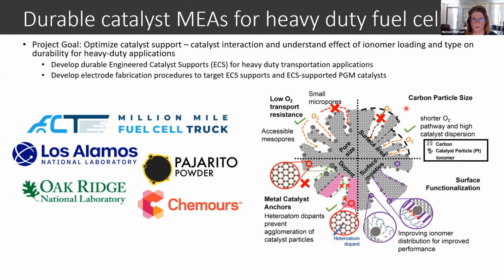From a carbon particle size perspective, we're very interested in being able to develop supports that have very short oxygen pathways, as well as supports that can facilitate very high catalyst dispersion. In the lower right-hand corner, you see a lot of emphasis we put on surface functionalization of our catalyst supports. And this is really to be able to improve things like ionomer distribution that improves the overall performance of our fuel cells. And then on the lower left-hand side, really looking at the importance of being able to effectively anchor our metal catalysts to be able to largely prevent agglomeration of these catalyst particles as they are used in many, many cycles.